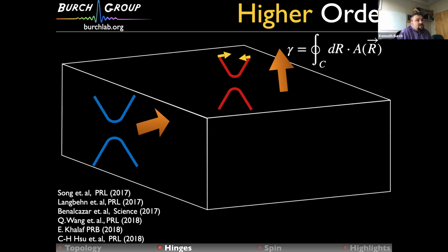And the catch is that these gaps have a sign associated with them, which is, how do I put this magnetic field? Do I put it along the c-axis or anti-parallel to it, right? And so I can think of it as having a positive gap on the top surface and a negative gap on the side surfaces. And so the result is, it must be that at the boundary of these two domains, namely the so-called hinge, I'd have a one-dimensional zero energy state, right? Which I basically can't get rid of.